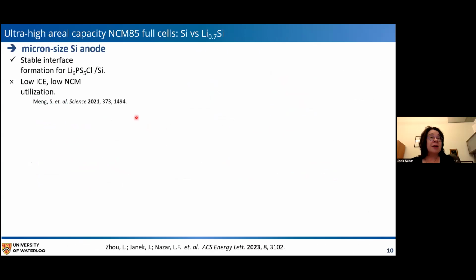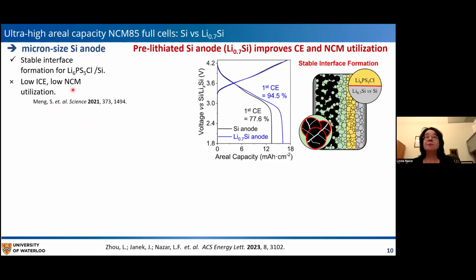So just another side point, there was a really nice paper by Shirley Meng's group in Science in 2021 showing that one could use micron-sized silicon particles as an anode instead of lithium indium, which we typically do use. And this also forms a stable interface for the argyrodite. But they did see low initial coulombic efficiency and not ideal utilization of the cathode material.